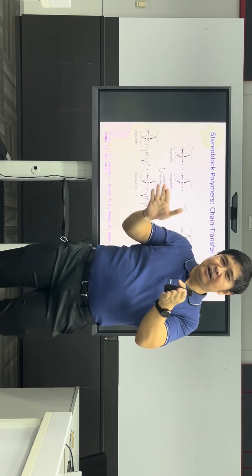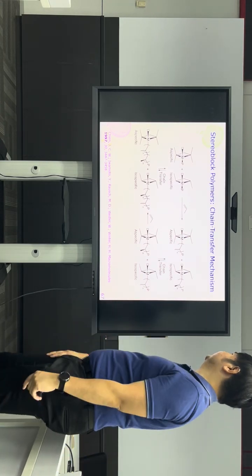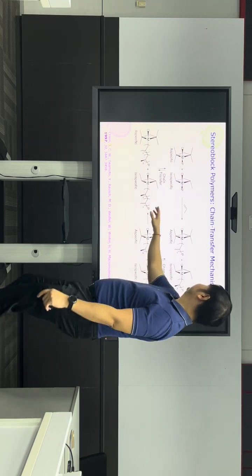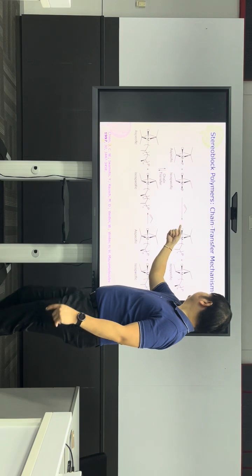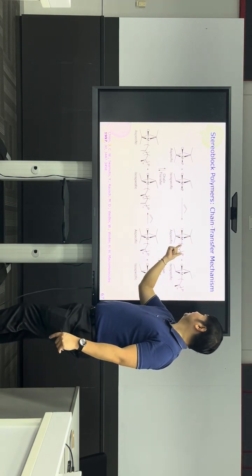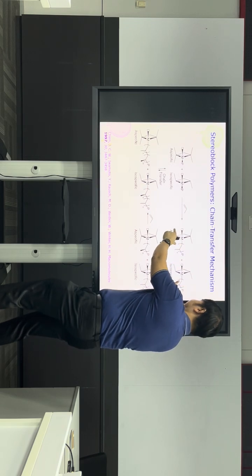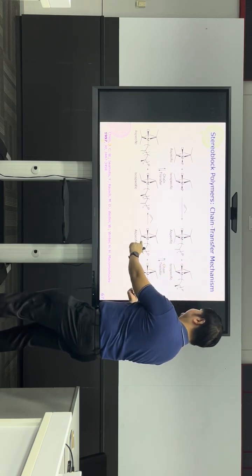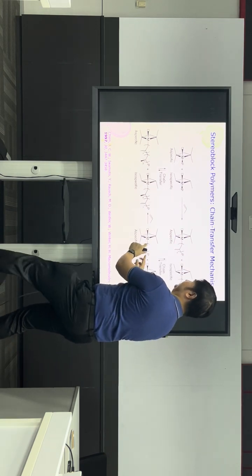So it will be a block of isotactic, a block of atactic altogether. It's quite a good idea. See, from here you have this catalyst, right? A specific one makes you random, and then this group is the transfer switch, basically switching to give you this. See, this is a switch here, this is a switch there, and after you do more polymerization, actually isotactic is now added